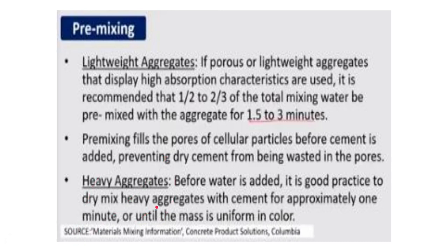Heavy aggregates. Before water is added, it is good practice to dry mix heavy aggregates with cement for approximately 1 minute or until the mass is uniform in color. So basically, in the case of lightweight aggregates, 1/2 to 2/3 of the total mixing water should be pre-mixed with the aggregate itself before mixing of cement takes place, in order to preserve cement from being wasted in the pores.